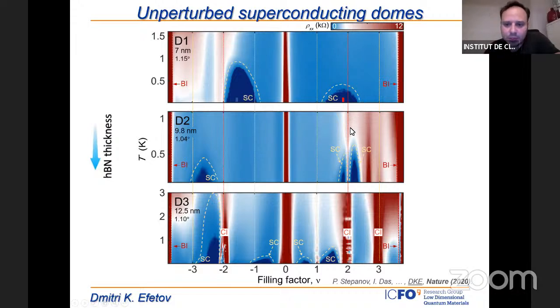Actually, if we now look at the intermediate layer, then we can see how one of those superconductors, which really penetrates across the integer filling positions, is now being interrupted by the correlated insulators. So basically, after we had those findings, of course, the narrative was that these correlated insulator phases and the superconductors maybe are not as connected as we originally thought. So it looks like changing the dielectric environment somehow affects the insulators quite dramatically, but it does not have such a big effect on the superconductors.